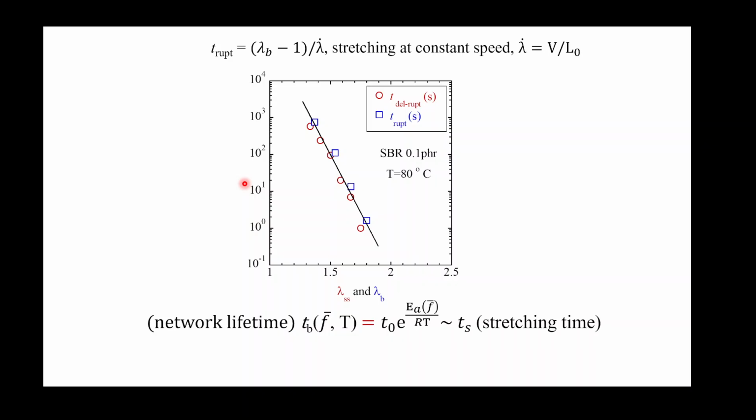So this beautiful step strain experiment teaches us that the waiting time is your network's lifetime. What's plotted in red was the step strain of different levels. You find if you stretch more, you wait less time, see? What's plotted is how much you stretched and waited. That's the red. And it turns out you can do the continuous. You find the breaking in continuous stretching matches in the sense that the slower you stretch, because you're given enough time, the lifetime, you only need a small amount of stretching. So basically, this confirms my theory that the reason you break is you reach the lifetime of this.